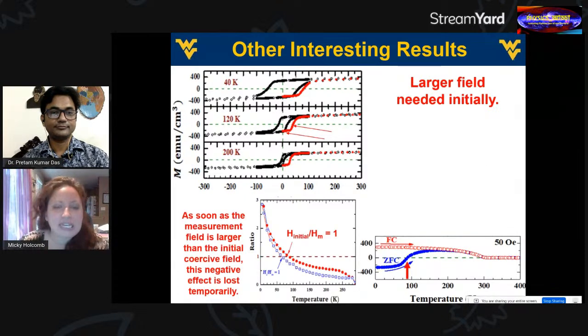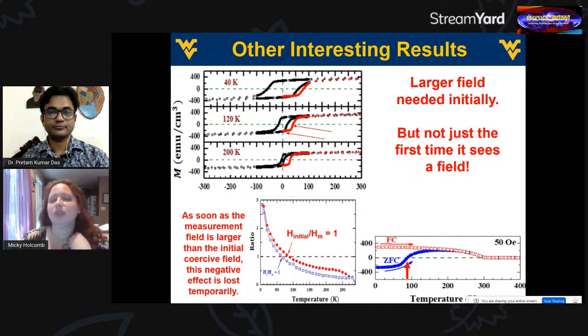Also, you can relate what this initial field is needed to switch. So you'll see here I have it measured at various different temperatures. This field, if you relate it to the measurement field that you're doing the measurements in the last set of curves that I showed, you can actually look at where the fraction is 1, and that will show you where this zero field cool curve switches from negative magnetization to positive magnetization. So this initial field is where this switch occurs. All right, some cool stuff.